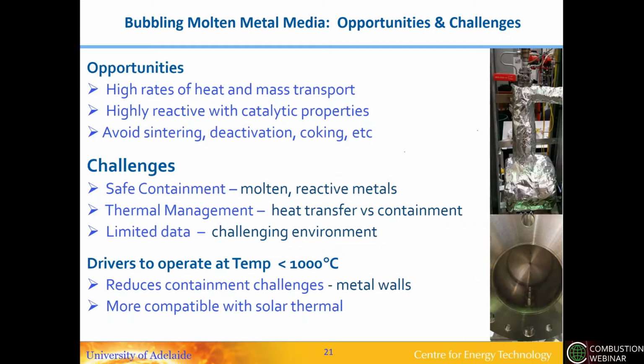And so therefore the surface of the catalyst doesn't get deactivated, and hence it becomes continuously replenished, the surface at least. On the other hand, there are challenges, including safe containment of a hot molten metal, and also the thermal management, how the energy is going to be converted into this reactive media. And also there is really very limited data on this, because obviously it's not very easy to perform measurements inside a molten metal bath.